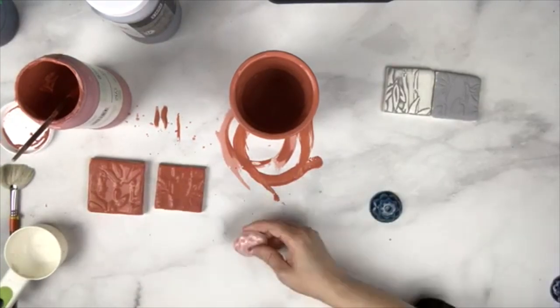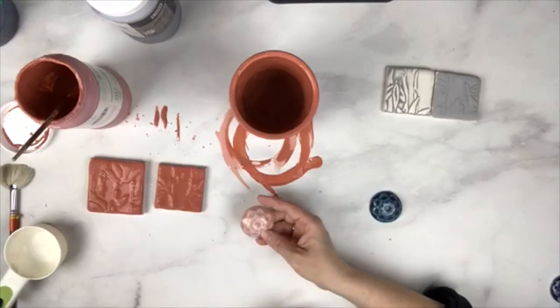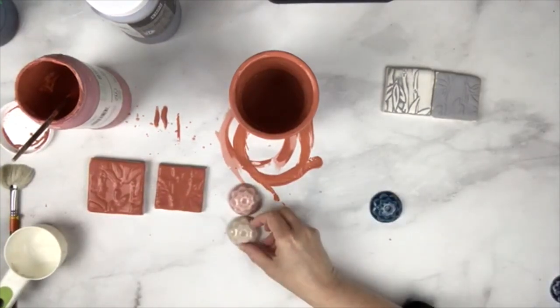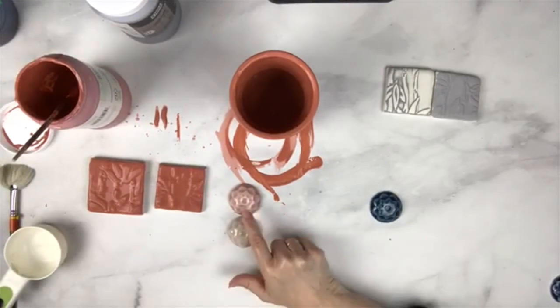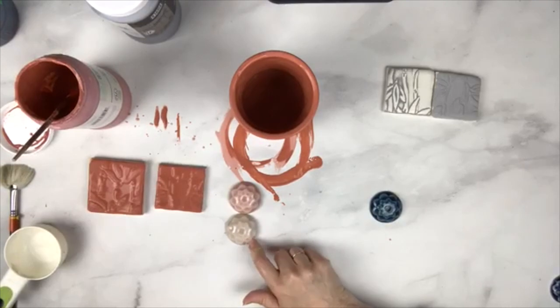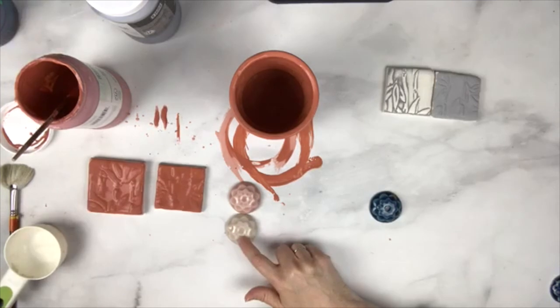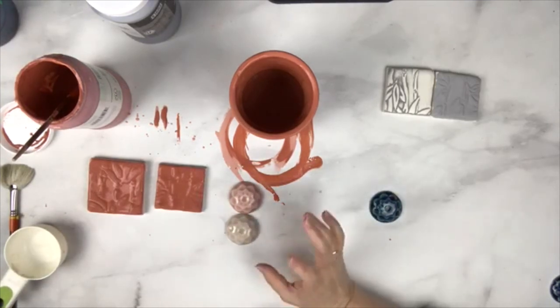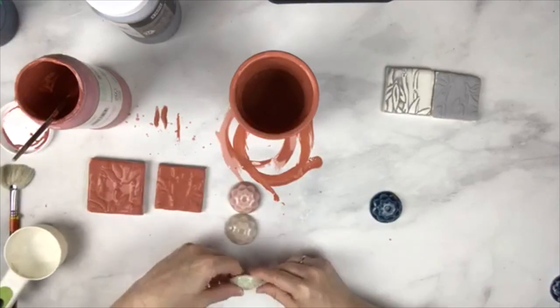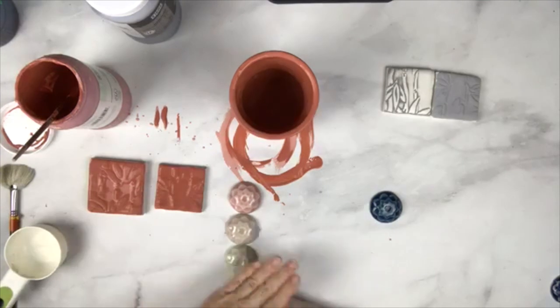This is the cherry blossom that I showed you on the platter in part two. This is at cone six, and this is at cone seven. A lot of times if you're having a problem where your cherry blossom is not coming out pink, it may be over-firing, especially if you're using a particularly long hold. As I mentioned in last week's live video on ancient copper, if you're using a hold longer than 10 minutes, you may be pushing up into the next cone range. The amount of heat work — which is temperature and time, not just temperature — means you're actually pushing up to cone seven. And at cone ten it completely loses all of its pink.